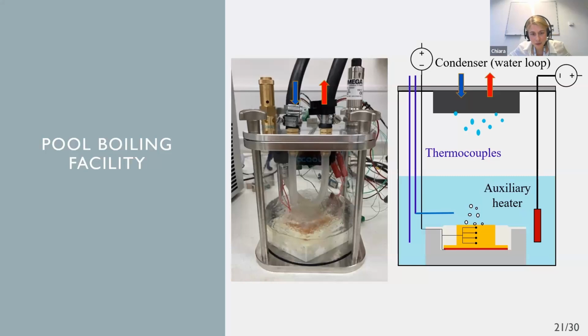But if we move to a different type of aircraft with different flight modes, then immersion cooling has to be reevaluated. If the operations are below a few seconds, it's still okay, because the electronics can operate a few seconds without the fluid, but that would be an extra step. In relation to this, there is a very nice study carried out by a larger consortium of European universities with the European Space Agency, where they studied pool boiling on a space station. In that case, there are even effects of different gravity conditions. To address that, they investigated different surface types to try to push bubbles off the surface even when gravity is not helping.